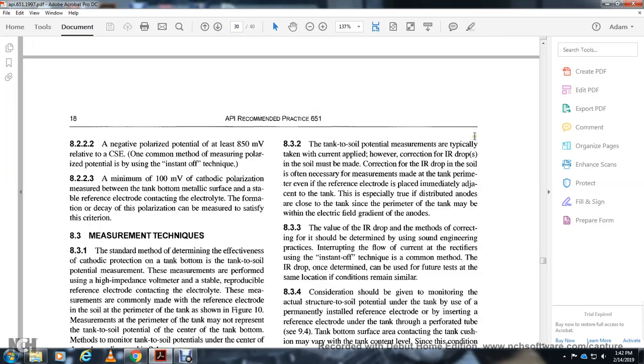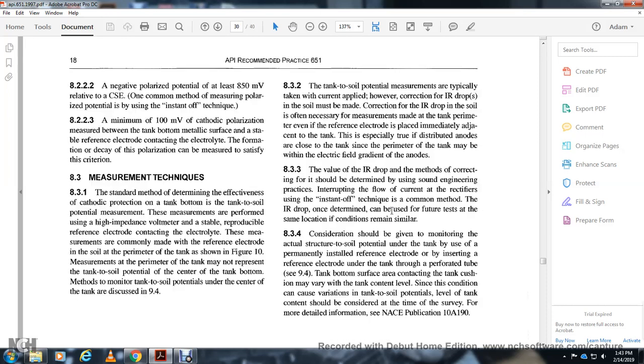8.3.2 Tank perimeter potential measurement. The typical measurement carried out at the tank perimeter may require correction for the IR drop, which is often necessary when the measurement is made with the reference electrode immediately adjacent to the tank. This is especially true with distributed anodes close to the tank, where the electrode may be in the voltage field gradient of the anodes. The value of the IR drop and the method of correction should be determined using sound engineering practice, interpreting the flow of current from the rectifier.